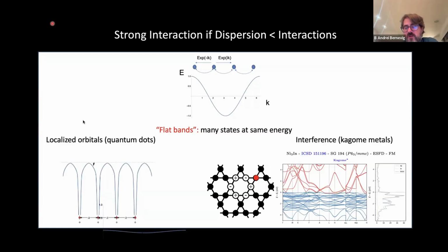as the electron moves, as the momentum of the electron moves around. But you can see that the reason for this non-dispersion is not that the electron is pinned at sites. Why? Because if it was pinned at sites by a negative potential, then no electrons could move from one side to another. If no electrons could move from one side to another, then the energy of the electron would just be the energy per site, some negative energy, so you wouldn't have any dispersion.